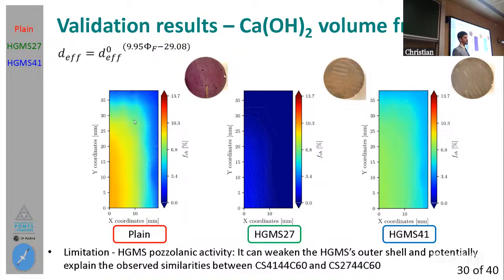So let's begin with the results obtained for the calcium hydroxide volume fraction across the cement specimens in the plain cement paste. There you will see that we have a pattern of colors indicating that in the innermost part we have a roughly unaltered cement paste, and in the outer part a more altered cement paste due to carbonation. But we never reach a zero content of calcium hydroxide, which is more or less what we obtained from the pH indicator test, where the outer part didn't appear to have a low pH, so we can relate that there.